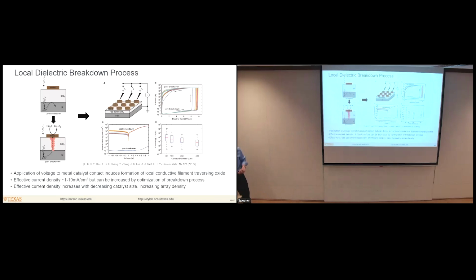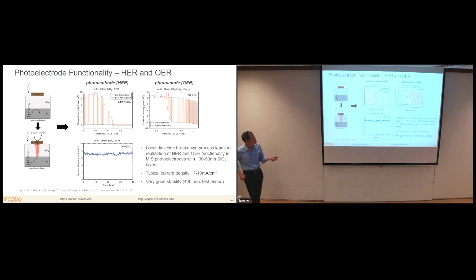The student who was working on this, Li Ji, went ahead and optimized the conditions for inducing this kind of filament formation and made both photocathodes for the hydrogen evolution reaction and photoanodes for the oxygen evolution reaction using this approach. The performance was reasonably good and the stability was very good, and it was generalizable to both electrons and holes. You could use different insulating layers and, in fact, even different semiconductor absorbers.